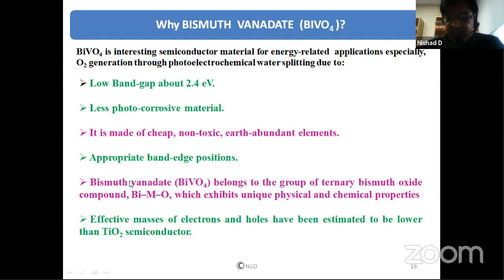Secondly, bismuth vanadate belongs to the ternary bismuth oxides, where the Bi-V-O bond structure is present, which makes it more unique, because this crystal structure has different kinds of forms, and you can deal with different kinds of facets of bismuth vanadate. Not only that, it has an effective electron-hole mass, which is quite exciting as compared to TiO2 semiconductors. That's why we are utilizing bismuth vanadate in our study.